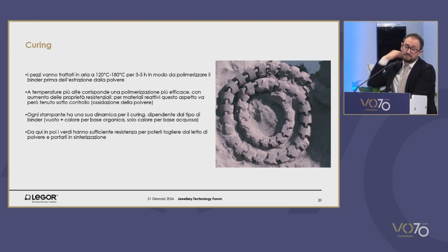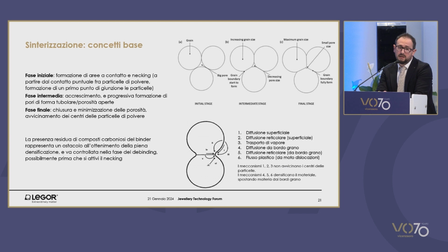And it has to bear in mind that some materials might be reactive. This is the case of silver and bronze. Therefore, the curing process for these metals, which is carried out in air, could lead to tarnishing, to oxidation. And oxidation may be detrimental to the sintering phase.